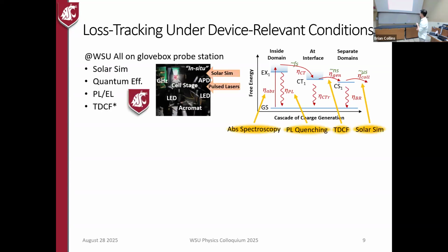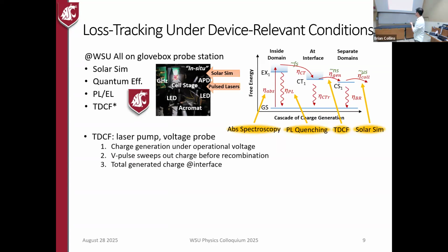And so in our lab, we've set up a way to quantify each of these steps in the charge generation process. One example is called time delay collection field, TDCF, which is a laser pump voltage probe measurement. This is what Case Patterson has been working on in my lab, where you generate charge with the laser pulse while you're holding the device at operating conditions. You allow all of this process to happen, so the charges either separate into free charges, or they recombine on the order of nanoseconds.